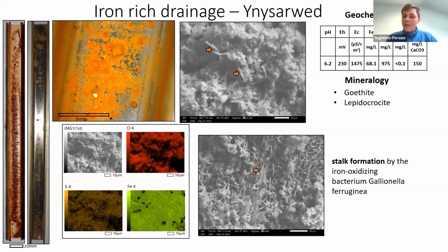During this coupon experiment, I investigated 4 sites, and the choice of the sites was of course arbitrary. We chose them because they have very different water chemical conditions. We have iron-rich sites, which can represent the more classic coal mine drainage in the UK: water that is rich in iron, oxygenated, where the chemistry is probably driven by pyrite oxidation, and alkalinity is not very pronounced. So I'm going to start by talking quickly about Ynysarwed, which is a very iron-rich site.